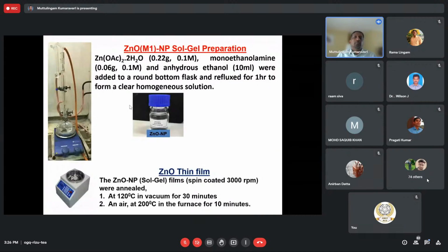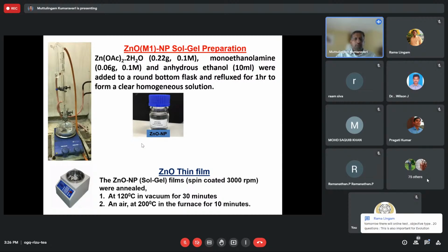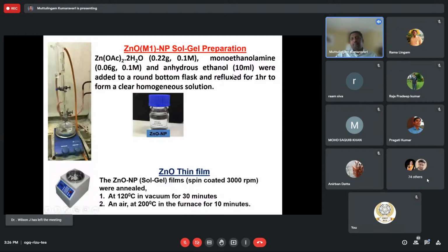First, we take zinc oxide. How do we make zinc oxide? That zinc oxide we use for QLED manufacturing, where it works as the ETL, the electron transporting layer. We use zinc acetate dihydrate, 0.22 gram, 0.1 mole. Then monoethanolamine, 0.06 gram, which is 60 milligram, added with 10 milliliter ethanol in a round bottom flask and refluxed for 1 hour. We will get a very clear homogeneous dispersion.